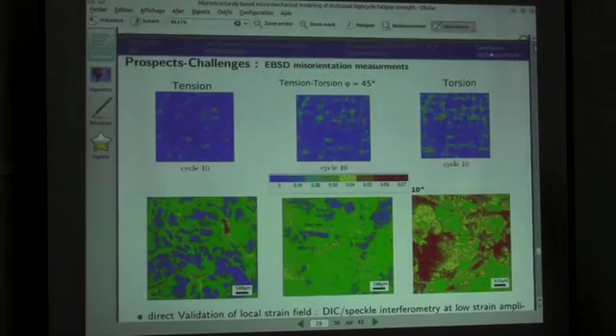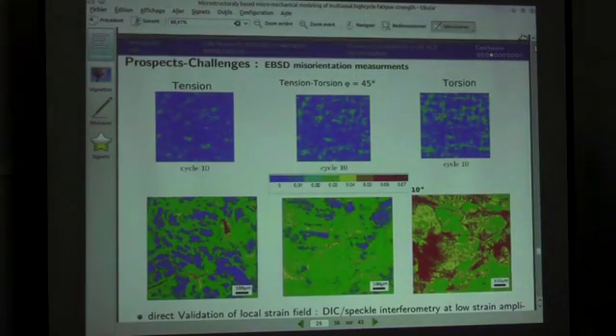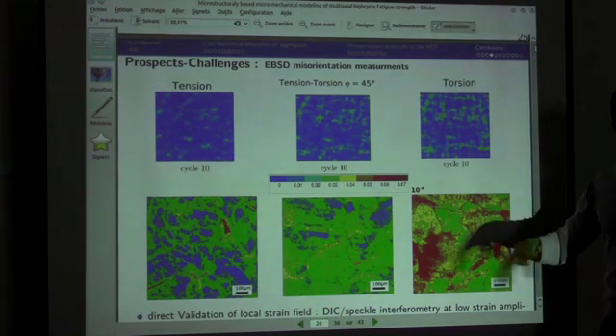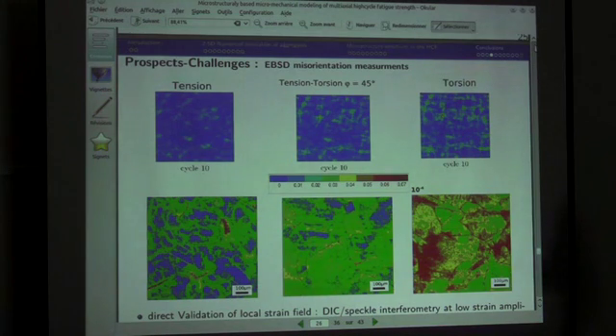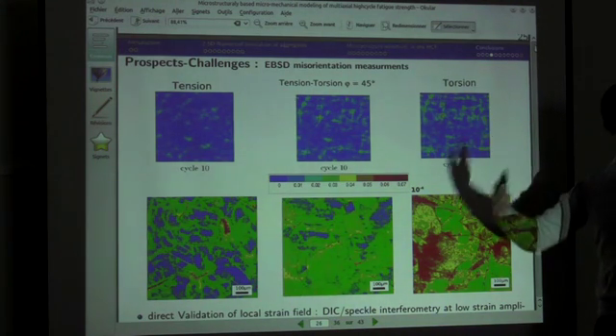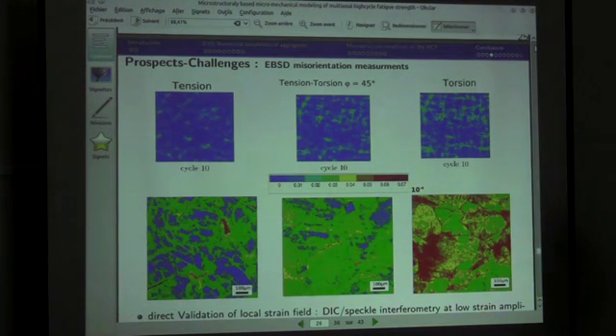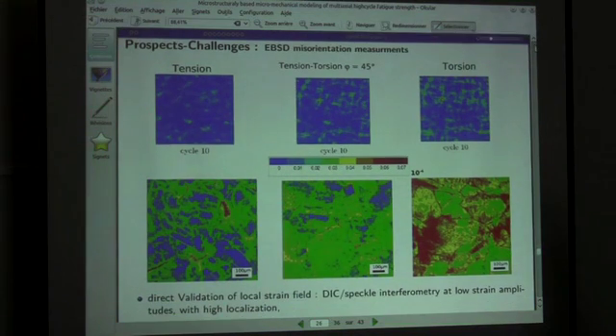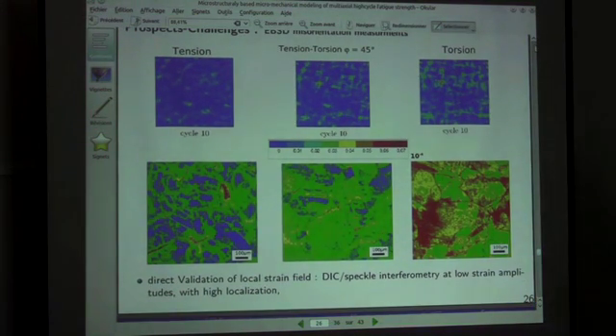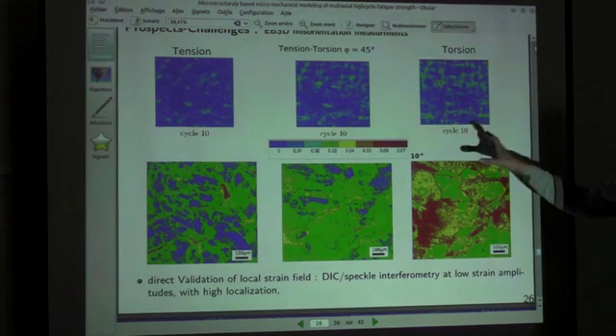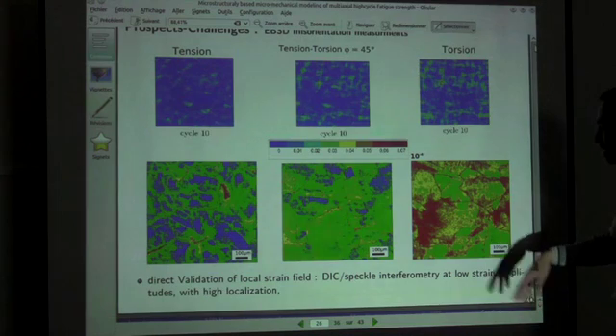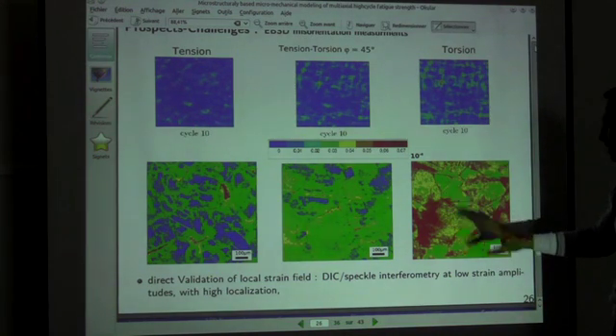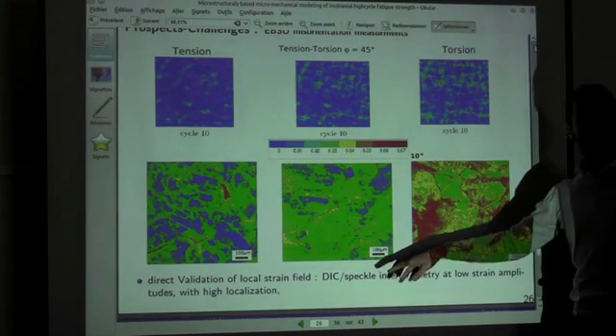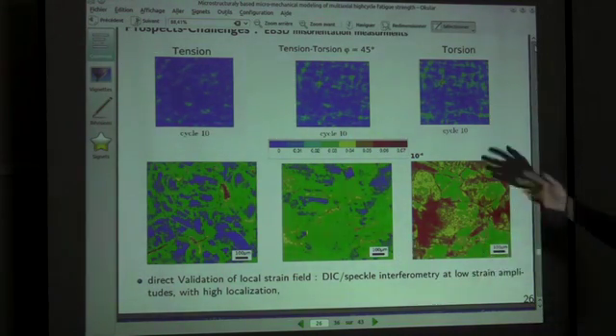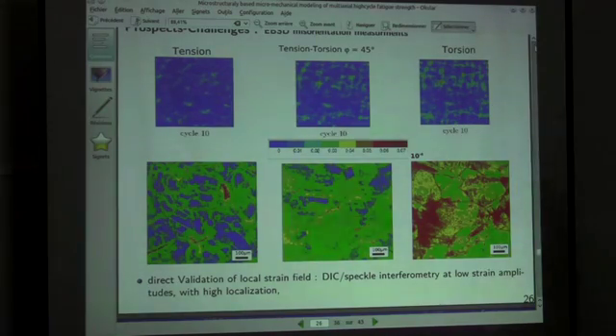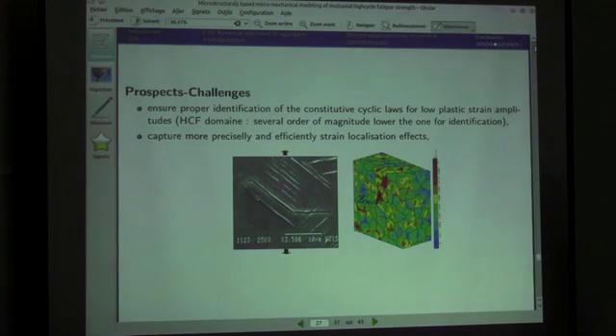What we have been trying to do is use the EBSD technique. EBSD can give you information about misorientation. So misorientation is plasticity. If you analyze the misorientation distribution, you can maybe have a way to compare your modeling to your experimental results. But still, it's quite difficult, and I do not know many techniques able to give sufficient information at the local scale to ensure that what we are computing is correct. Of course, we can think about the DIC techniques or speckle interferometry, but still we are facing some problems due to localization, for example. So this is the first problem.